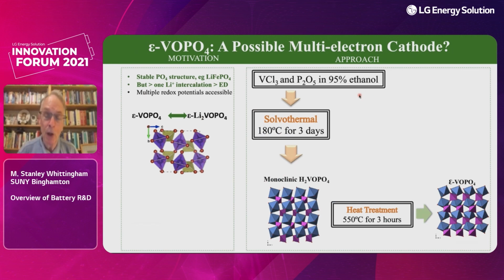You just dissolve all the reactants in a solution, heat it up to about 180 degrees for 1 to 3 days. We'll then get this structure with protons in it. And the reason we don't use pure ethanol is you need a bit of water to stop over-reduction of vanadium. If you heat this up, then you get all the protons out and get this empty lattice.